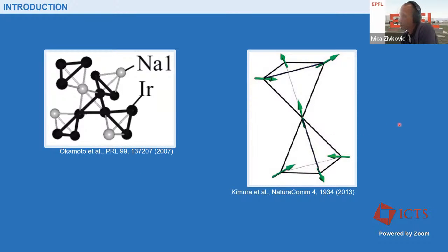On the right-hand side, there is a pyrochlore lattice, which has a long history, starting in the 90s, with the discovery of spin ices and all this beautiful emergent electrodynamics carrying magnetic monopoles. But there, again, one has to emphasize that that was realized in dysprosium and holmium, which have large magnetic moments. Only later there were realizations of materials with praseodymium, which has effective spin 1/2, and then, starting with this publication, substantial evidence of quantum spin liquid behavior in the pyrochlore lattice.